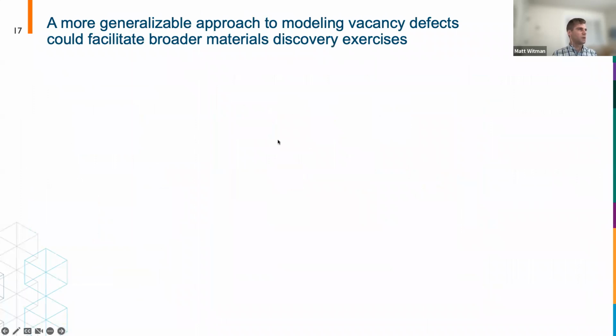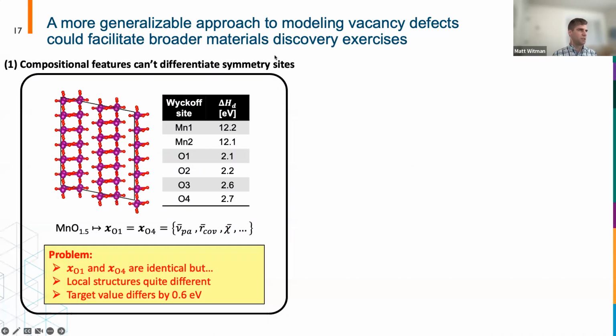And so our goal is to come up with a very generalizable approach to modeling these vacancy defects to enable this new materials discovery exercise. So some things that won't work, for example, are a compositional featured machine learning model, because you won't be able to differentiate the different symmetry sites. So if you have something like manganese oxide, you have different symmetry sites for these different oxygen atoms, in which the relaxed vacancy formation enthalpies can differ by 0.6 eV.